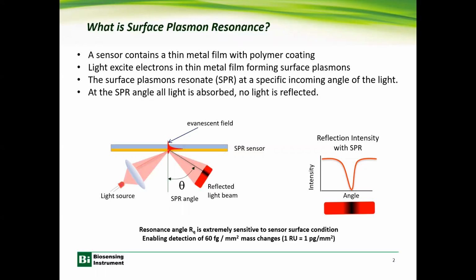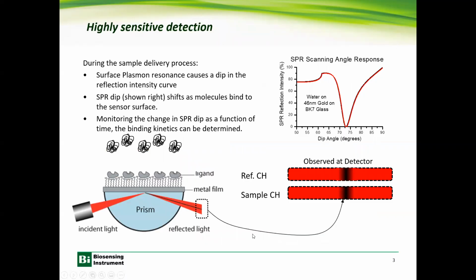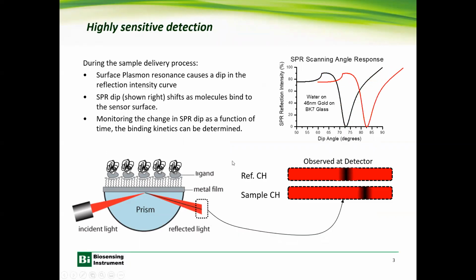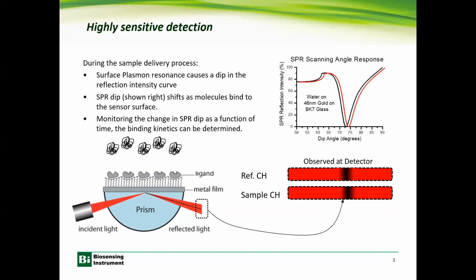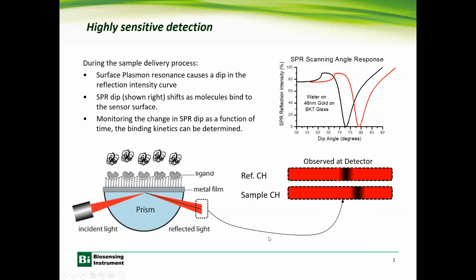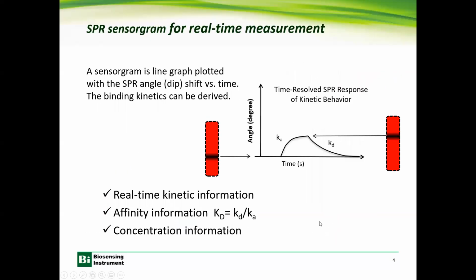So one of the applications is to use this technique to measure the binding of chemical reactions, the binding constants between molecules. In that case, we have the surface plasmon resonance set up, and then you have one molecule fixed onto the surface, which we call the ligand. Then you start putting in another molecule, and when this molecule binds to the ligand at the surface, it will cause a shift in the SPR angle or the SPR response. Depending on the stage during the reaction, you will see the SPR angle shift constantly. And you can record this SPR response, the SPR angle, as a function of time for the whole process of this binding reaction.